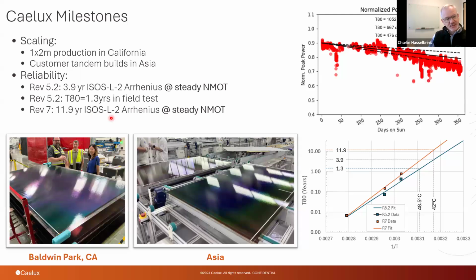If you test it at ISOS L2 and you create an Arrhenius plot out of that, and you ask the question of where will we be at our normal module operating temperature, which we've calculated as 42 degrees, we would see a significant improvement of Rev 7 over Rev 5.2. That's drawn with these lines. And then you might ask, okay, but what do you really see in the field? The actual field result that we've gotten with the same Rev 5.2 chemistry was about 1.3 years T80. And if you draw that line back over here to this plot, you'd say, well, why were you hotter than your normal module operating temperature?